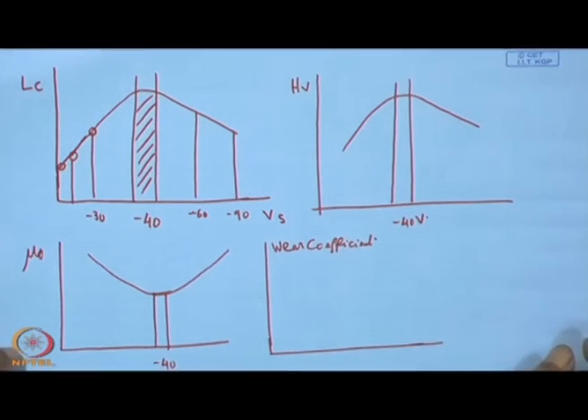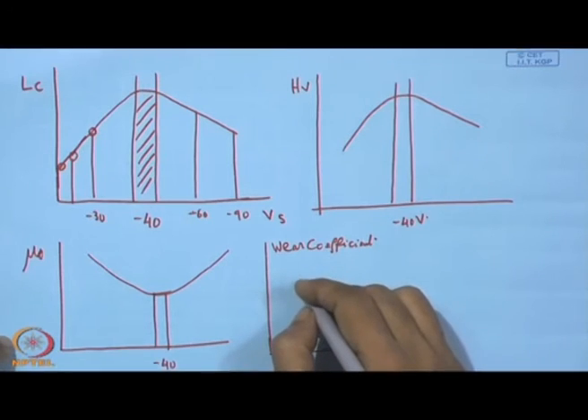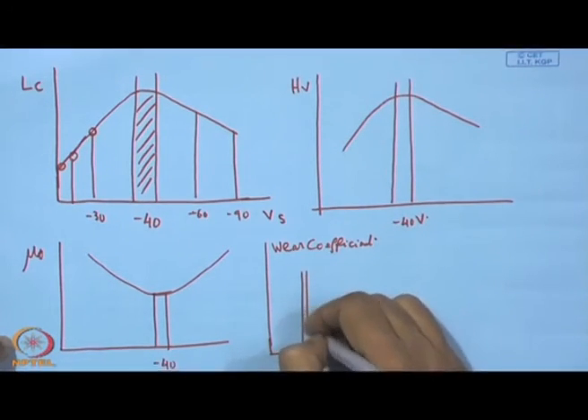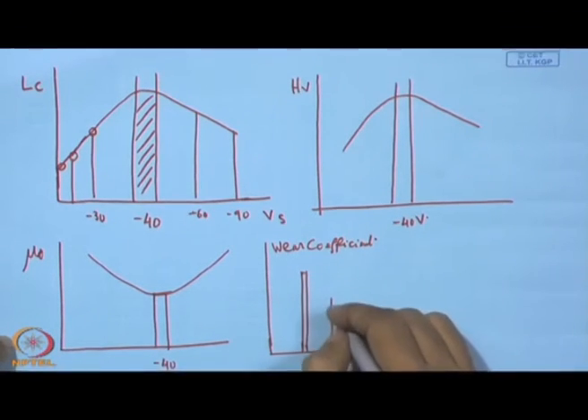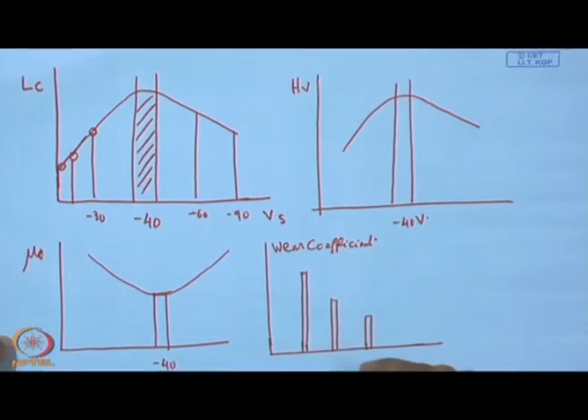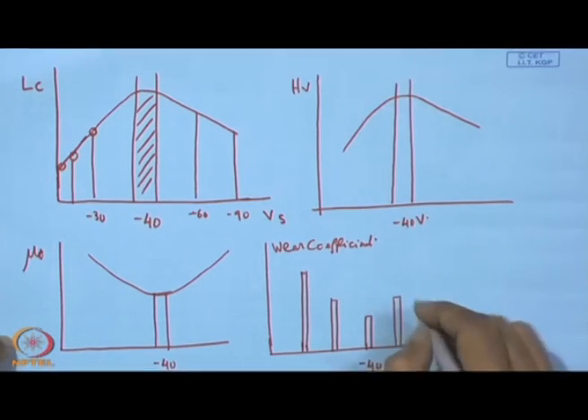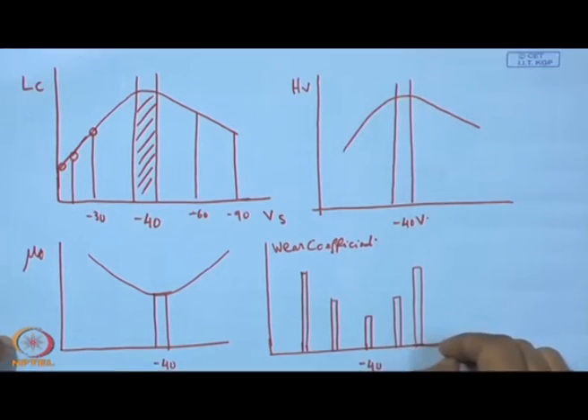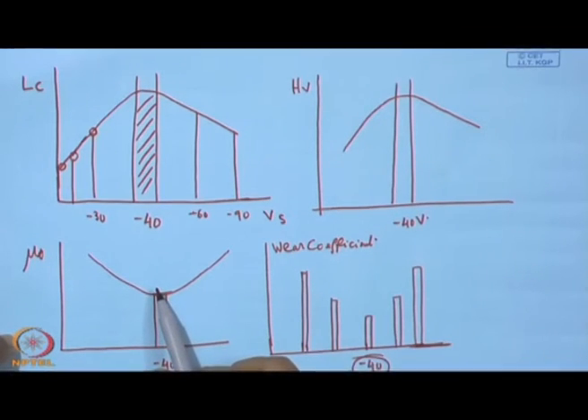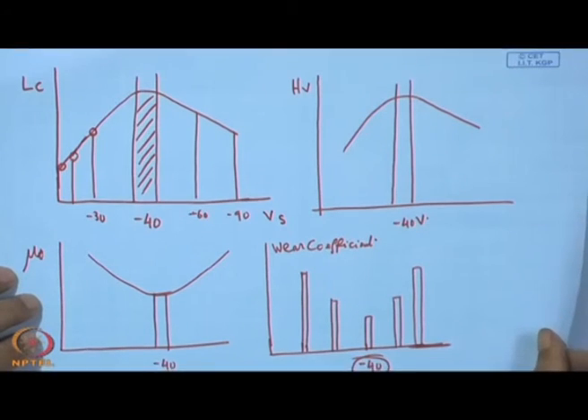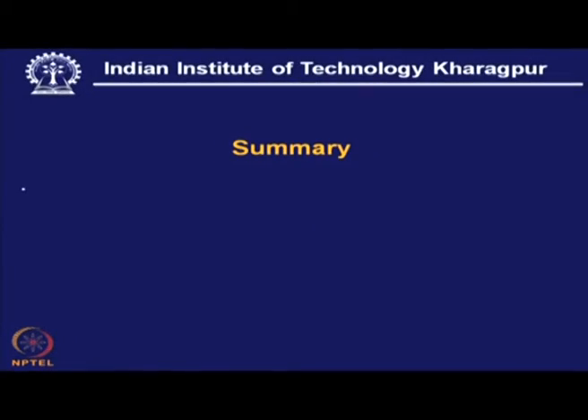So, this is a measure of wear on the ball or also on the disc. Here also we find that we have a high value with low bias, but somewhere around an intermediate value of minus 40 we get one of the lowest amounts of wear, and that is because of the hardness of the coating and the low value of the friction, and with this the coating can give one of the best possible performances in actual practice.